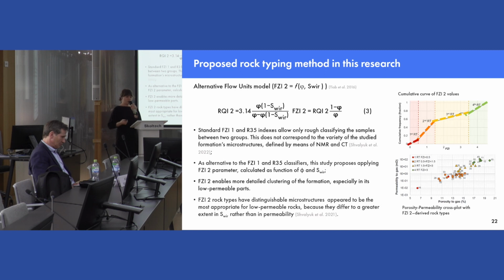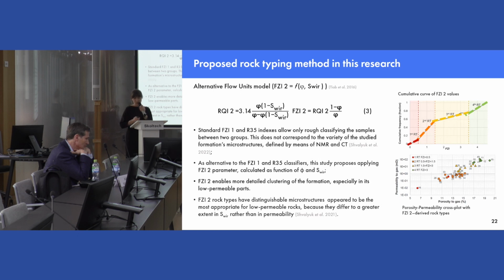But the alternative technique, which I propose, enables more detailed clustering of the formation, especially in low-permeable parts. And this alternative technique has enabled identification of distinguishable microstructures. And it appeared to be the most appropriate for low-permeable layers. And this is caused by the fact that these rocks mainly differ in irreducible water saturation rather than in permeability.